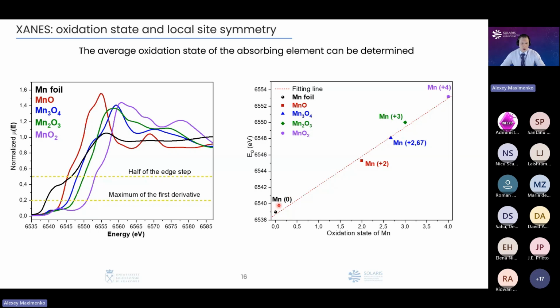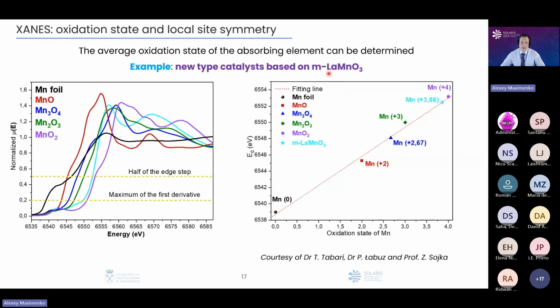For example, when you would like to work with manganese atoms in your material to investigate the average oxidation state, we plot a straight line based on the reference compounds, and we would like to investigate the average oxidation state of our unknown compound, for example, some new catalyst based on lanthanum manganese O3. When we put the position of the edge, which we define as half of the edge step, onto this straight line, we could define the average oxidation state in our newly produced material. But also, a very important thing we need to do when we make such an analysis: all of these references should have the same ligands around our absorbing atoms.